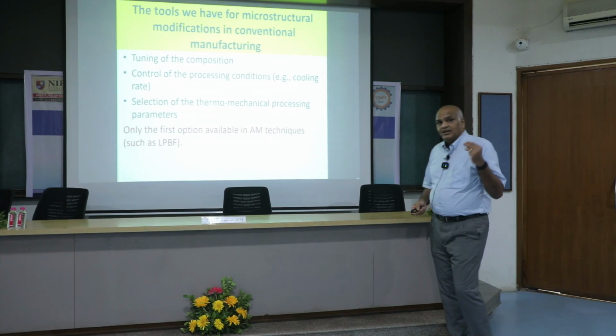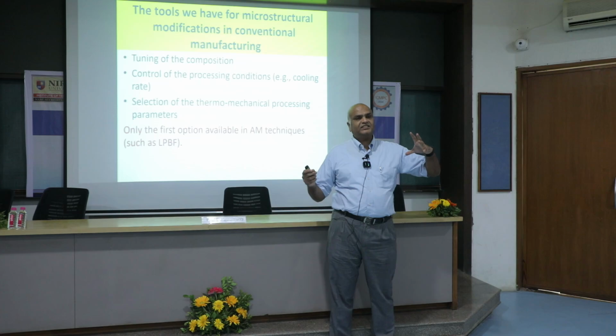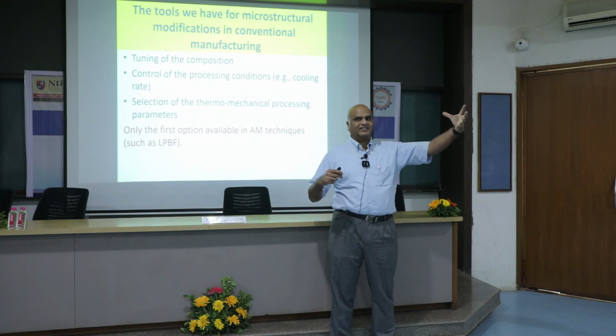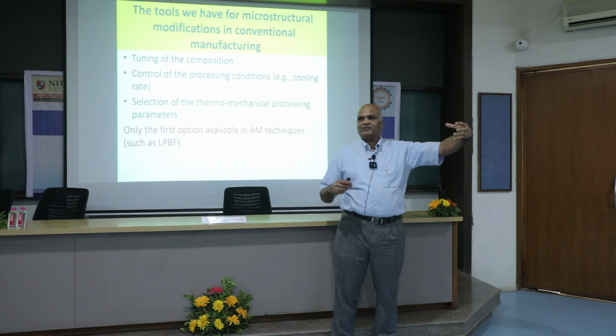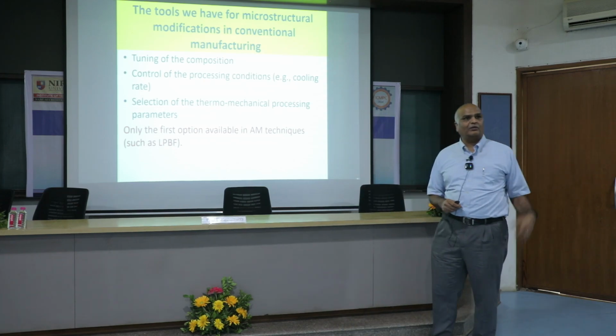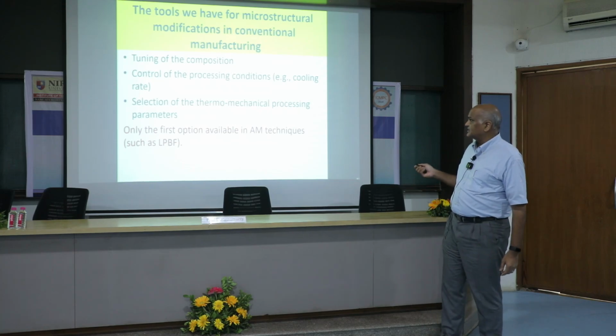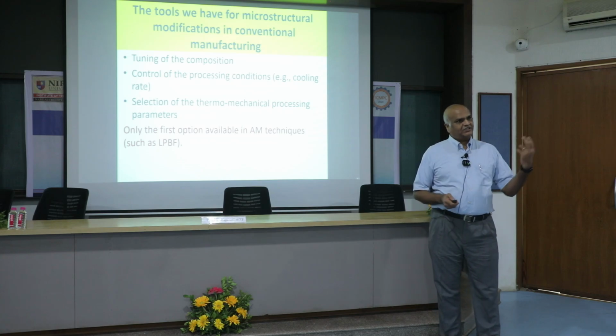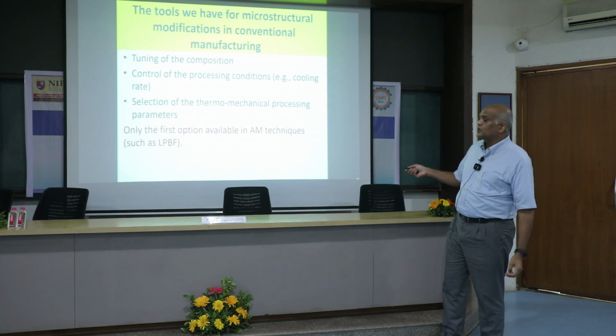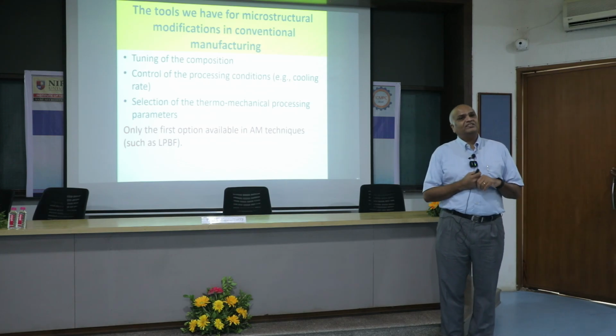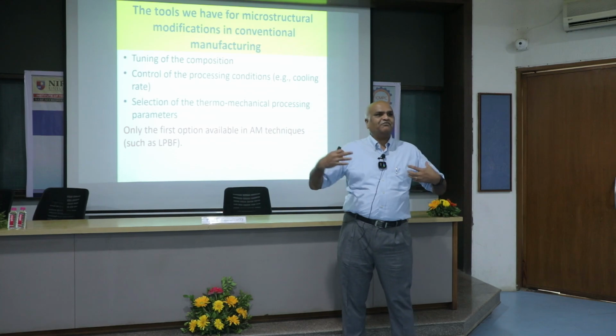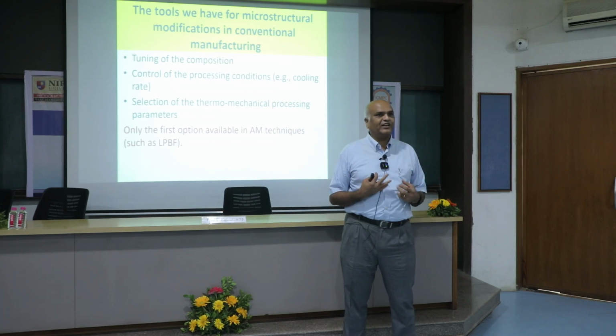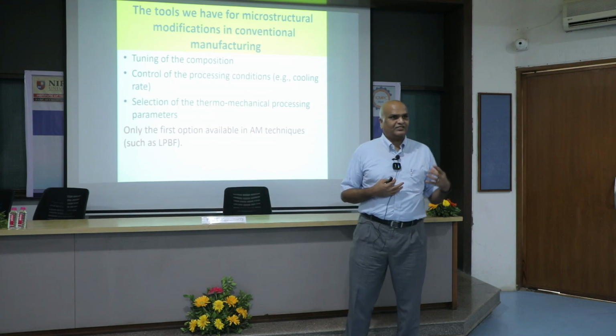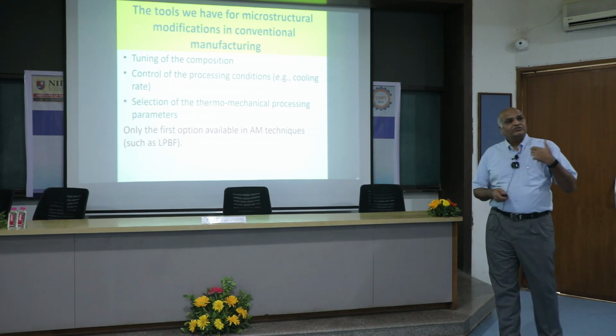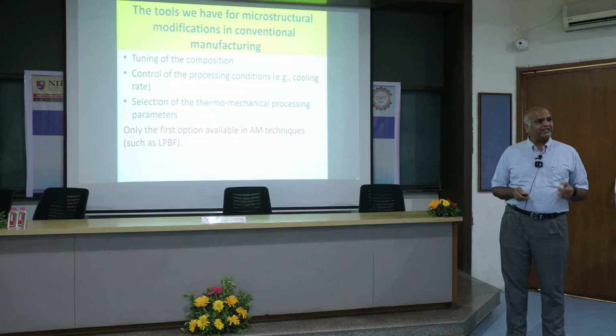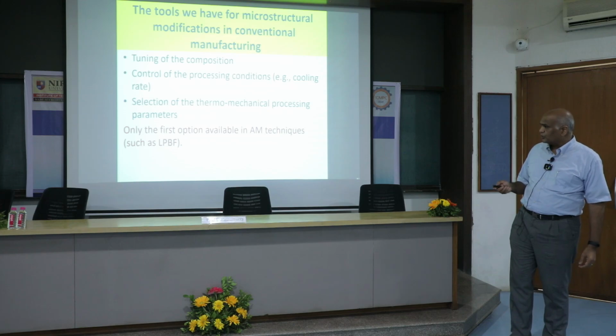Okay. Now, I already mentioned this, right? So in conventional manufacturing of metals, microstructures are very critical. And for tuning the microstructures, for designing the microstructures, I told you about the three tools that I have: composition, okay, and then I have processing conditions and thermomechanical processing, right? Now, I can still vary the composition for 3D printed parts, but the other two are not there, right? So this is a major challenge, right? The thing is, I don't have the kind of design freedom, the degrees of freedom available for designing microstructures, not component. I don't have it, okay? So this is a challenge, but we have other avenues to tailor the microstructures in these materials. And hopefully I'll show you that.